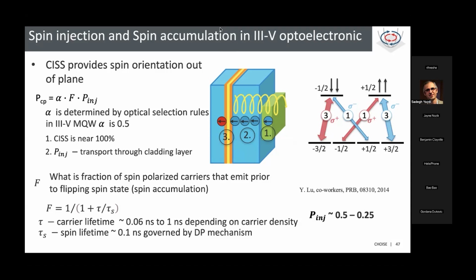And there's another caveat here, and that is the spin orientation is out of plane, not in plane. So we normally get in-plane with a ferromagnet, but this gets out of plane. So there are a lot of advantages for that, for all sorts of different potential applications, but for this one, it has some benefit for the direction that light is being emitted in, the polarization.